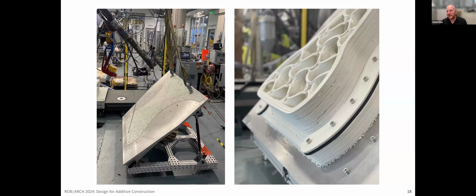So we took some notes from some other things we had seen. What we have here is an aluminum plate anchored to a structure at 45 degrees. You can see when we craned it into place. We have also pellets that are adhered to this build plate in the shape of the first layers. And then as we were going, the solid aluminum build plate has some structure on the back to keep the build plate itself from warping. And then once we got to about 100 layers, we'd also designed in a support structure. So you can see in white with the bolts going through it, an aluminum clamping plate. And so once we had started the print, we were able to clamp the piece to the build plate for the rest of the build.